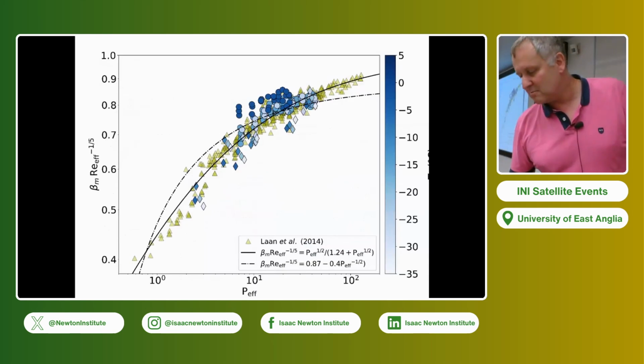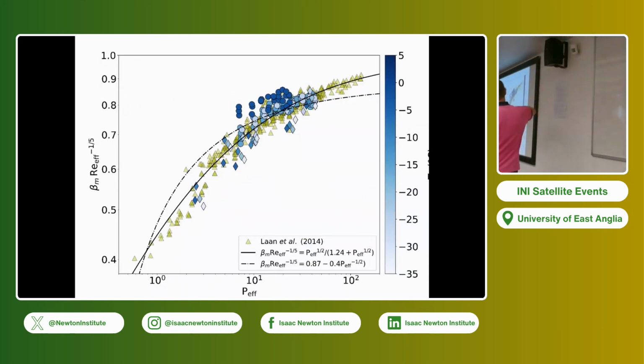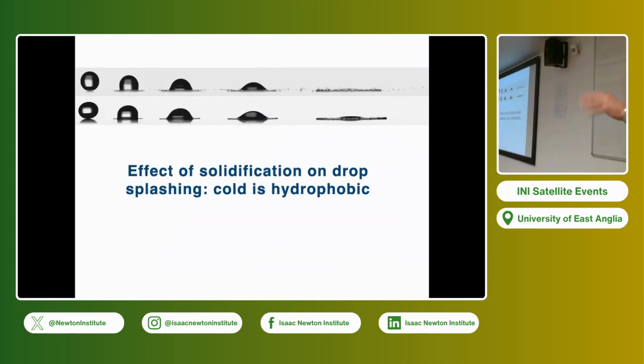If you just do this simple adaptation, you can put all the data on the same curve. The triangles are for the case without solidification and without melting. But if you add all the data we got by dropping onto a solid surface and dropping onto ice, you have all these blue ones. And if you consider the correction, that means you correct the Reynolds number by this additional solidification layer, you are able to put all your data on the same curve. We have a little bit more of an error bar, but it's still very good. Okay, I might stop there.